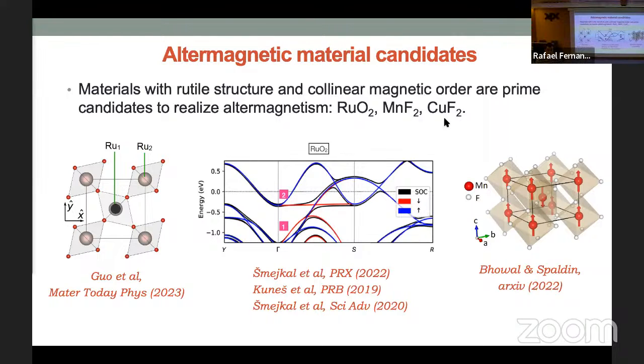If you do first principles, turning off spin orbit coupling is actually easy. You don't need to turn off anything. You just don't turn it on. And you can actually see that you get huge splitting. This is ruthenium oxide, in red and blue, and there is a big splitting here of order of an eV, which you'd never get if you had just spin orbit coupling. I'll later show a microscopic model that gives some intuitive understanding of why this splitting is so large. This splitting doesn't come from spin orbit coupling, it comes from hopping, and that's why it can be so large.